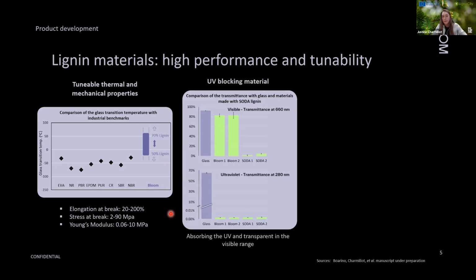So something else that we measured is the UV blocking ability, because lignin is known to absorb the UV. So we made some elastomers with this system, and we did the same with another lignin. And when we measured the visible transmittance, we saw, as we can see visually, that the Bloom lignin is really transparent, up to 80% of transmittance, whereas the other lignin materials were not. And regarding the ultraviolet, of course, as it contains a high quantity of lignin, all of them are really absorbing the UV. But this change of absorbance between the visible and the ultraviolet is really interesting and could open different applications.